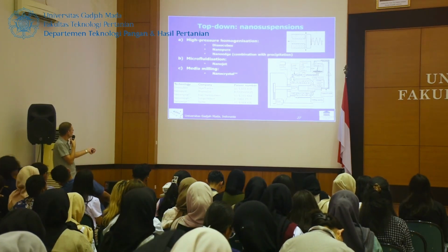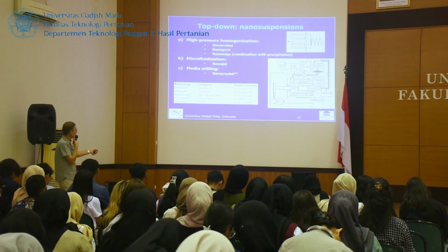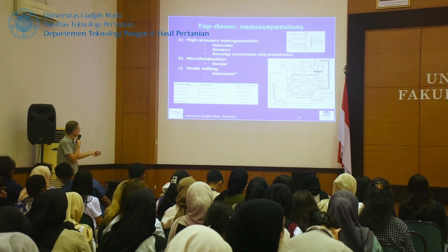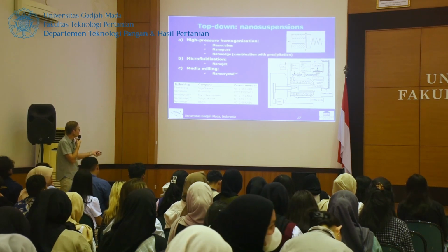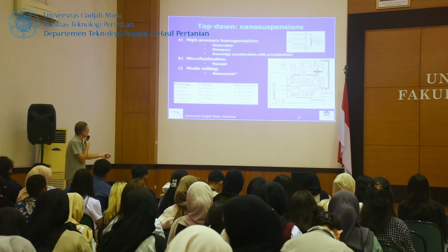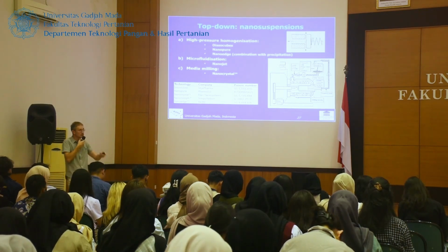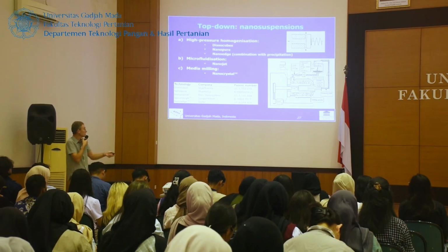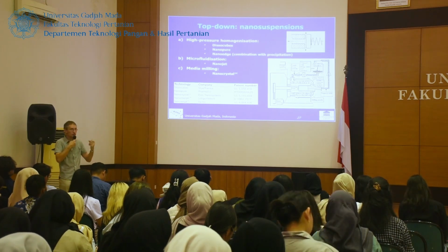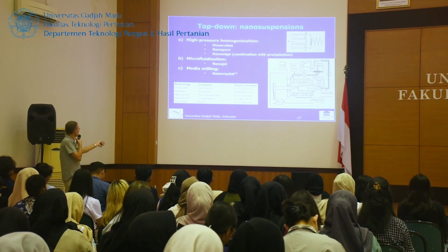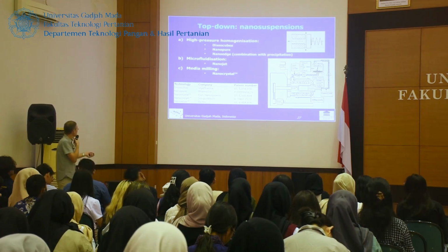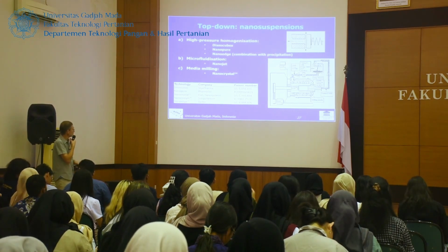And in this case, there's also a third technique. What can also be done with solid particles is a milling operation. Media milling means that you combine your suspension with other very hard particles. That whole suspension is then gradually, slowly stirred, so that the beads move over each other, and the particles present in between can be gradually ground and gradually reduced. In that case, we're talking about nanocrystal technology.